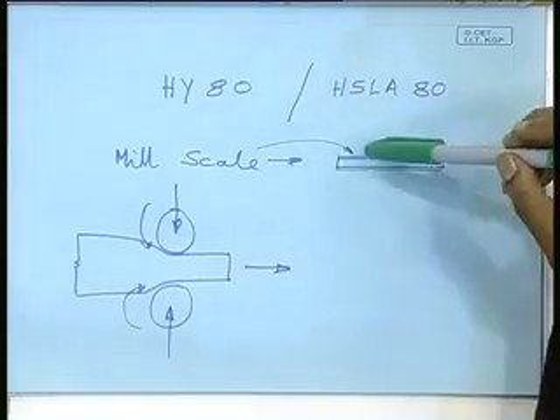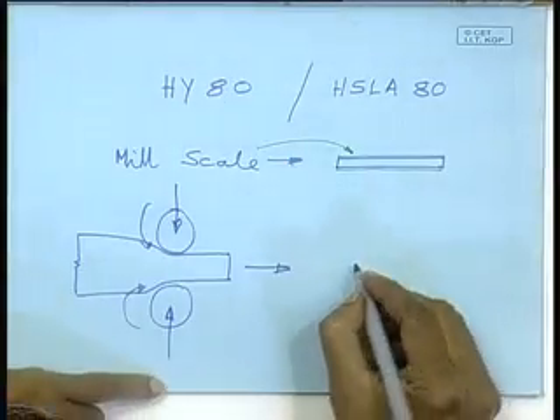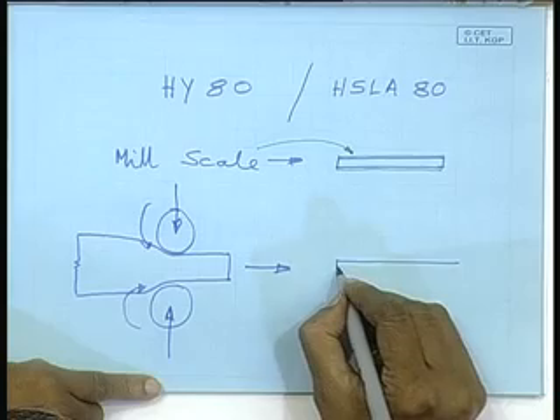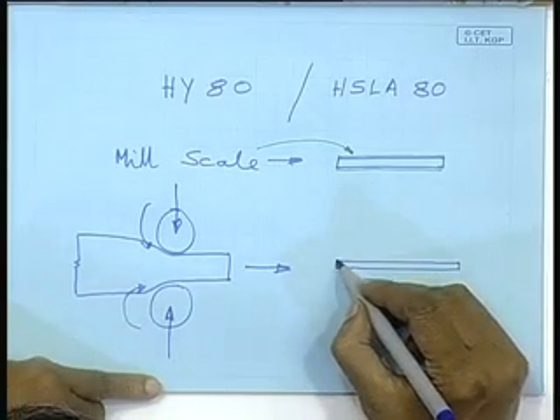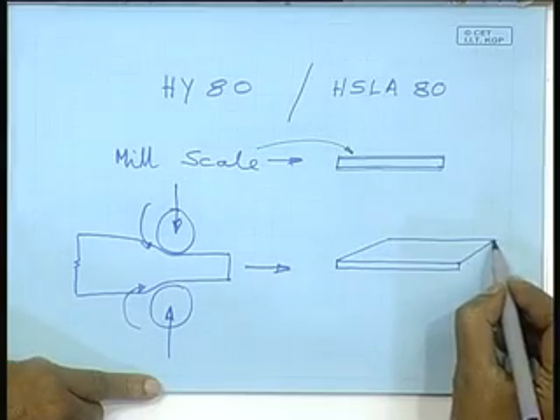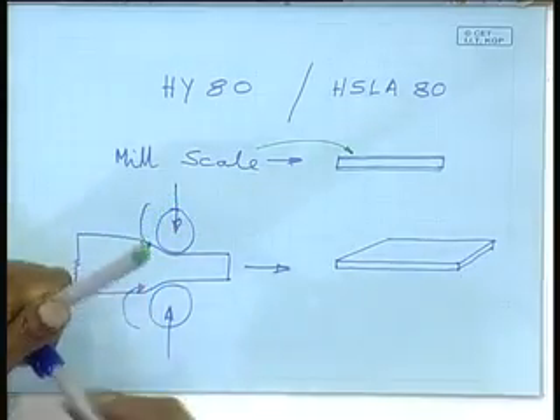So, what will happen to the surface when finally I get the steel plate out to my desired thickness, right? Suppose this steel plate has come out like this. So, what do I have on the surface? On the surface there will be oxidation taking place, because it was at a high temperature, exposed to open atmosphere. Thus there will be an oxide layer forming on the surface, right, and it is under pressure. So, in the process that layer of oxide will be firmly bonded to the plate surface. That layer is referred to as mill scale, right.